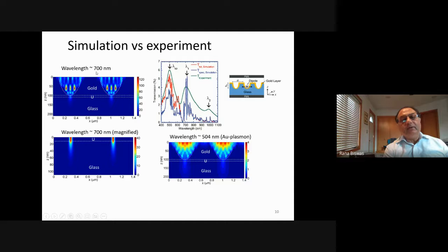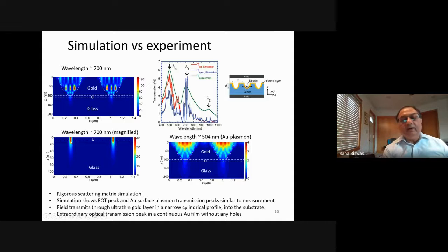And what you see here, if you sit at the resonance, 700 nanometers, there's a very high field that is localized within the nanocup. And this field penetrates through the bottom of the nanocup over here into the glass substrate. And it does that because there's an ultra-thin gold layer, which is much thinner than the skin depth. And it gives you this narrow cylindrical profile of the transmission into the substrate. So this is what leads to the extraordinary optical transmission peak in this continuous gold film. And if you look carefully at the scales of this, you will see that the electric field intensity is more than a factor of 100 higher close to the bottom of the holes.